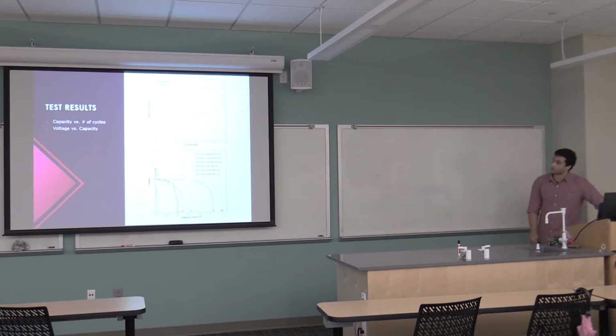The test results from this, so you can see in the top graph there, that's going to be the capacity versus number of cycles. So the bottom lighter gray dots show the non-TMV1cys-coated surfaces, and the darker dots show the TMV1cys-coated structures. And it's pretty apparent that the overall capacity, even from the very beginning, was greatly increased due to the coating with the virus. And the bottom one here is the voltage versus the capacity over 2 cycles, 15 cycles, and 30 cycles. So the dotted lines are uncoated and the solid lines are coated. And you see after about 30 cycles, it stabilizes at about a 2 times increase in capacity with the virus.